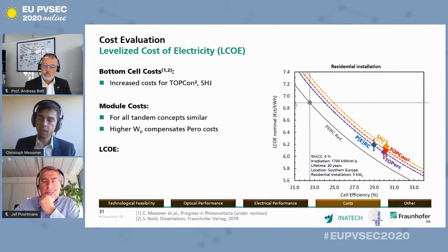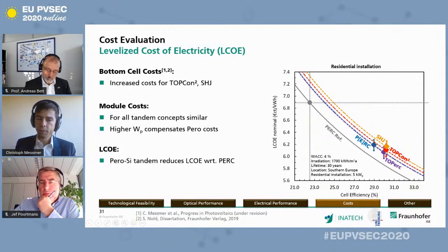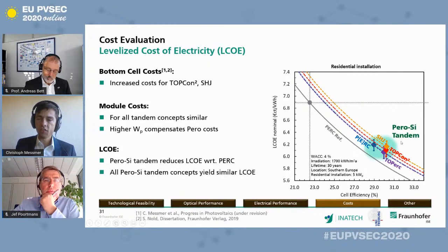So if we compare this then with our tandem devices, we see, first of all, that the costs would be higher for the same cell efficiency. However, we're lying around 29 to 30%, which ends up that all perovskite silicon tandem devices significantly reduce the LCOE with respect to the PERC single junction. However, we can also see that all perovskite silicon tandem concepts yield a similar LCOE within the uncertainties of our model.